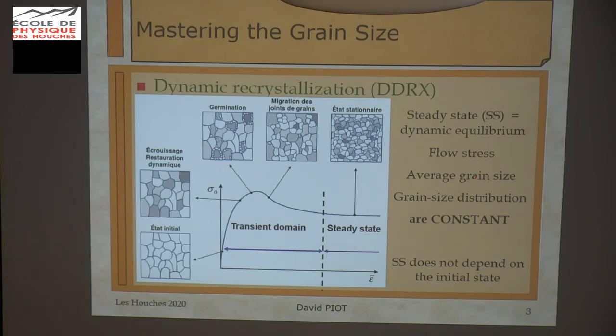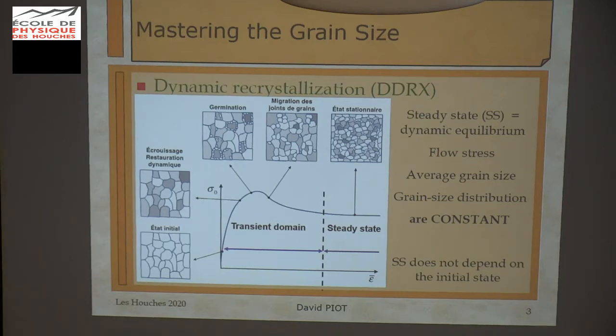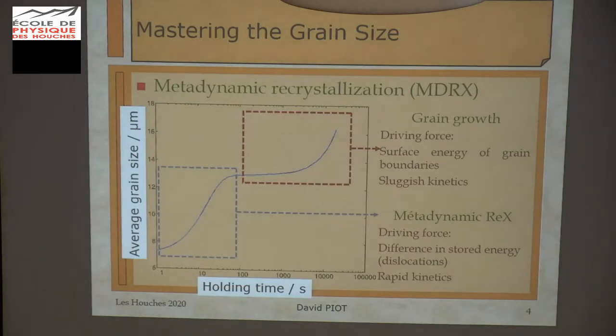The flow stress, the average grain size, and even the grain size distribution are constant. And this steady state does not depend on the initial state. It depends only on temperature and strain rate, if these parameters are kept constant during the test.